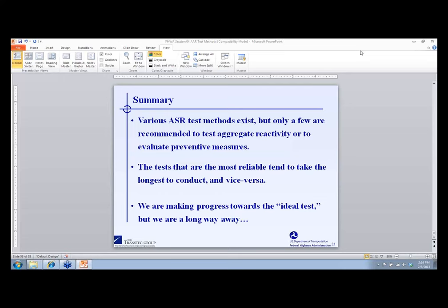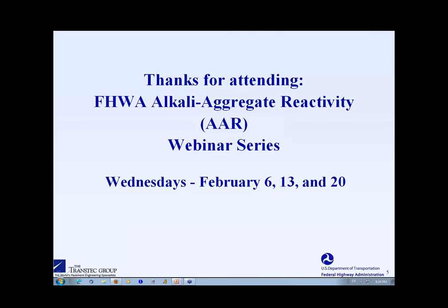The first question we have is, due to the saturation of the sodium hydroxide in solution in the C1260 test, does the cement's alkalinity matter? It's a very good question. Generally, the alkali content of the cement does not make a big difference in the accelerated mortar bar test because of the infinite supply of alkalis in the host solution. It does tend to make more of a difference when you evaluate SCMs, because higher alkali content in the cement will actually activate the fly ash or slag in the early stages, say in the first 24 hours, and that will actually have some effect on the test itself.